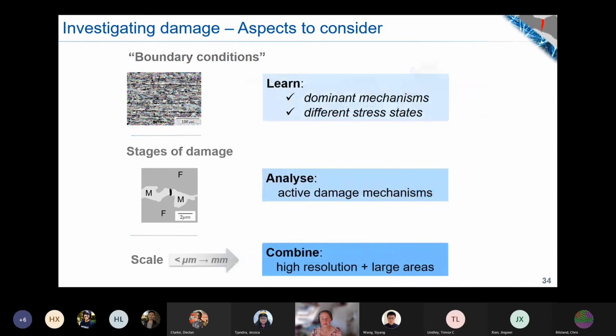So what I want to do here is show you how we started addressing this problem. The first step was being able to combine high resolution to look at individual mechanisms and individual sites, but do this over large areas so that we can actually look at inhomogeneity and get some statistical relevance. What we want to analyze is the active damage mechanisms, and we want to learn which ones are dominant and how that might, for example, differ with stress state. So whether I bend a sample or whether I pull on it in one direction or biaxially.